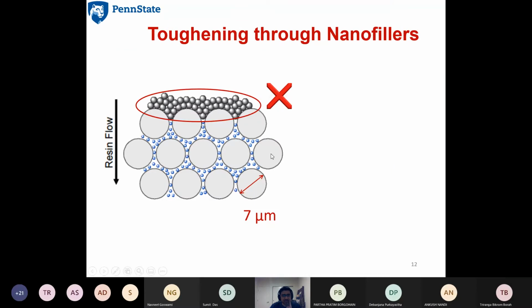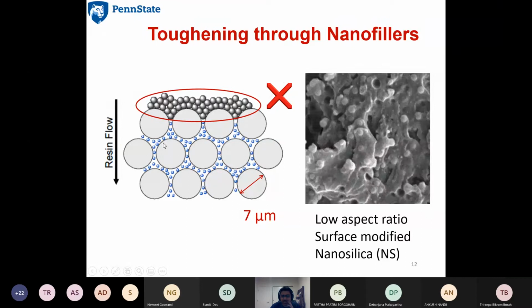So this is what we did. We thought that we'd add nanofillers to the matrix. Any fiber composite has two parts. You're looking at the cross section here. There's the carbon fiber and there's the matrix. The matrix could be a thermosetting polymer or a thermoplastic polymer. We were specifically interested in thermosets. So we wanted a nanofiller that can get between the carbon fibers, does not agglomerate, stays well dispersed, and is easy to make. So we went with low aspect ratio nanosilica particles.